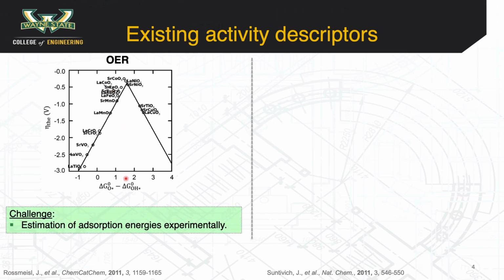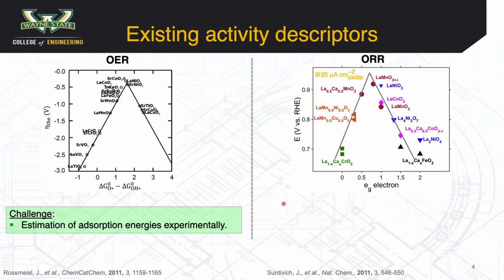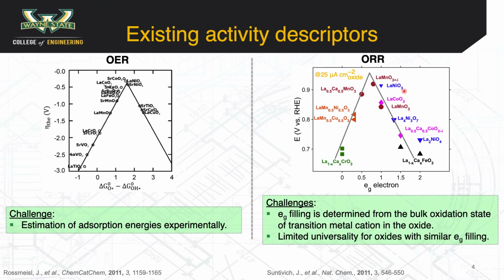One of the challenges associated with such theoretically calculated descriptors is that it is challenging to estimate the adsorption energies of reaction intermediates experimentally. In order to overcome some of these limitations, there has been some work towards identifying experimentally measurable descriptors. For instance, the Eg orbital filling of the transition metal in the oxide has been shown to exhibit a volcano type relationship with the experimentally measured electrocatalytic activity for oxygen reduction reaction. It has been shown that an Eg orbital filling close to 1 provides an optimal compromise between strong adsorption and weak adsorption, leading to enhanced catalytic performance. One of the challenges with such a descriptor is that the Eg orbital filling is determined from the bulk oxidation state of the transition metal cation in the oxide.